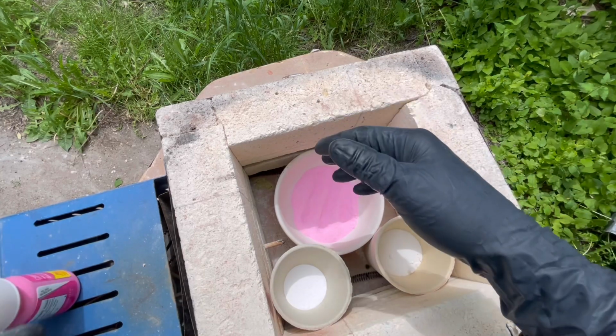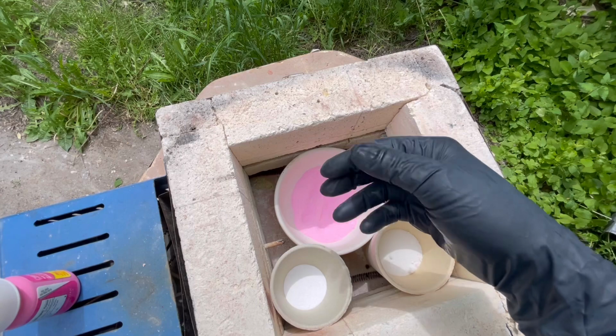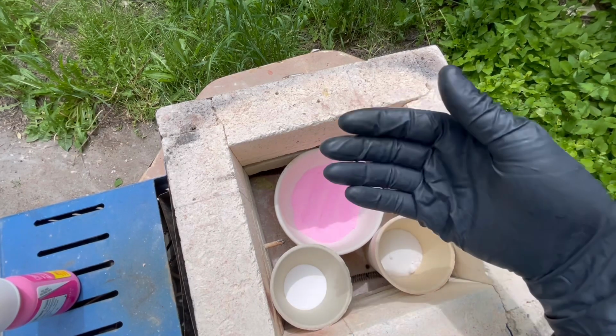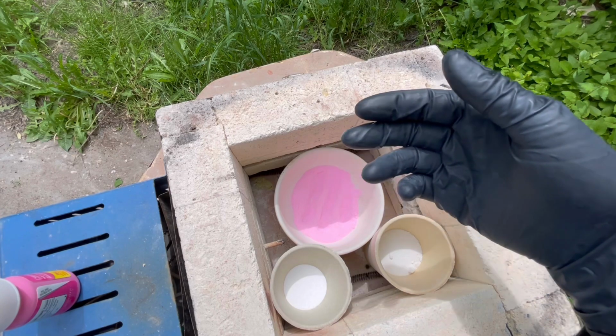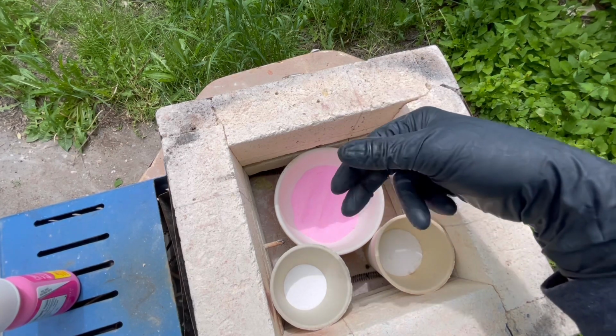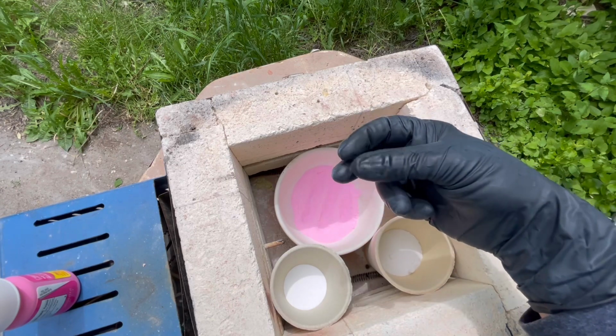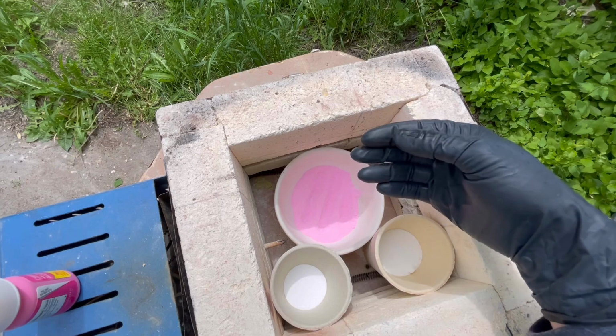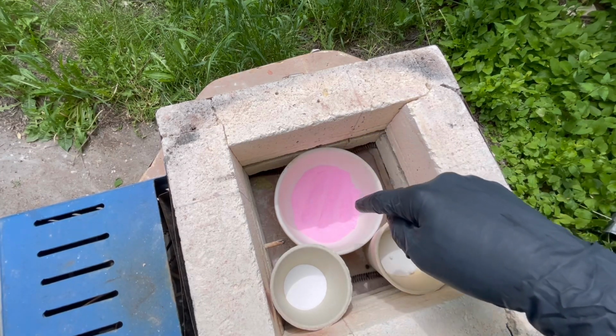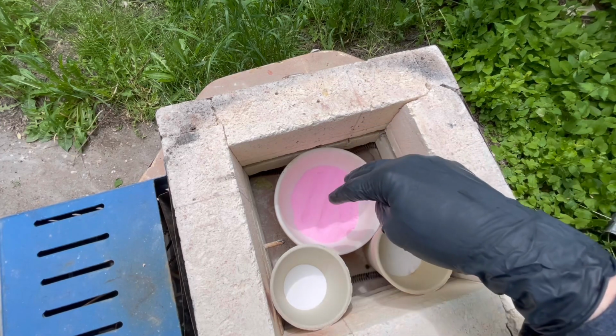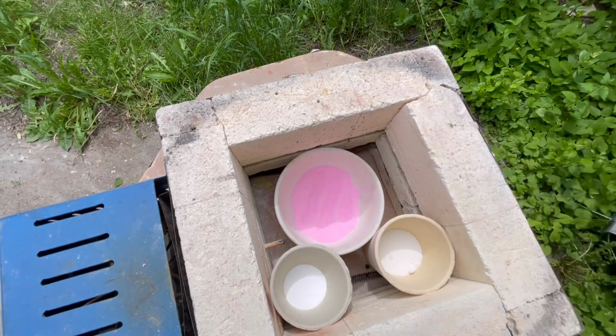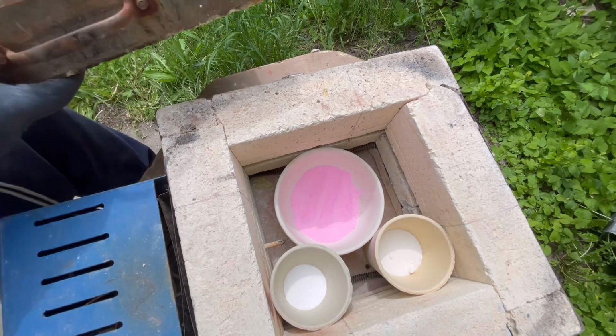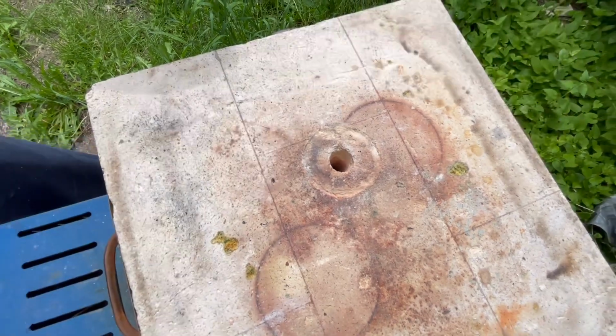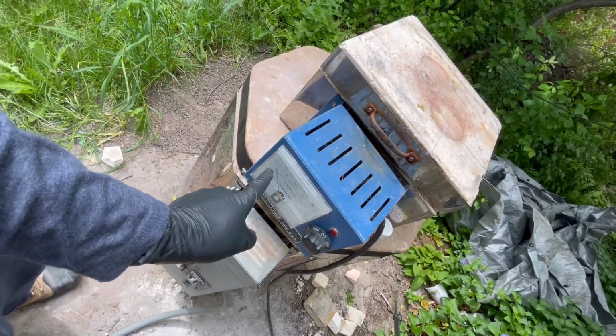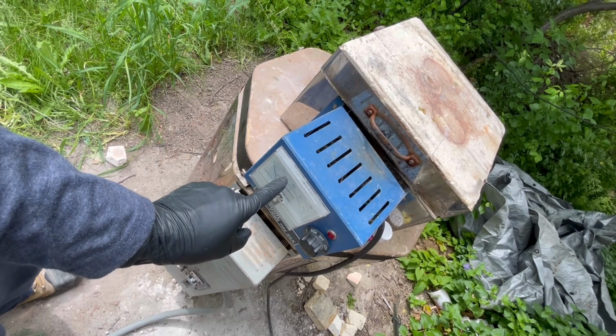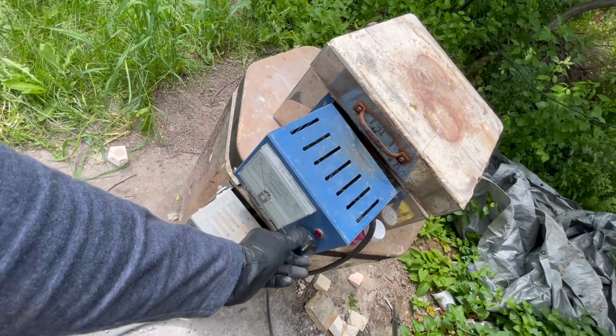You can still get away with it if you cook the sample for a really long time and wait for that carbon to float to the top and burn off in the oxygen of the air. But until that carbon all burns off, the sample will be very thick, it won't release the metal particles, and it just doesn't behave well. So it's much better to roast it beforehand to completely oxidize everything and then add the amount of carbon you need later. Okay, so hopefully I've explained everything. Let's put the lid on here, and I'm going to turn this on and cook her up to about 600 degrees Celsius, very slowly.